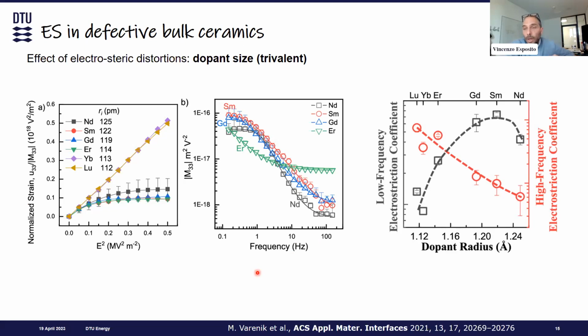And here we have a paper from Weissman, from Lubomirsky, that shows this dependence. And interestingly, we can also discriminate between two possible different mechanisms at low frequency and at higher frequency. And here at high frequency, I mean around 110 Hz max, because whatever we have above that value is extremely low. So we actually lose the properties above around 110 Hz.